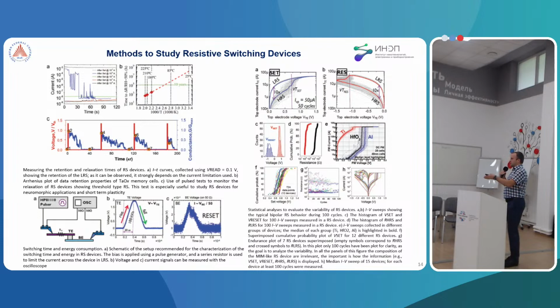On this slide, on the left figure, we can see a schematic of the setup recommended for the characterization of switching time and energy. The bias is applied using the pulse generator and series resistor is used to limit the current across the device in the low resistance state. After that, we measure voltage and current signals with the oscilloscope and present on the figure the time of resistive switching.